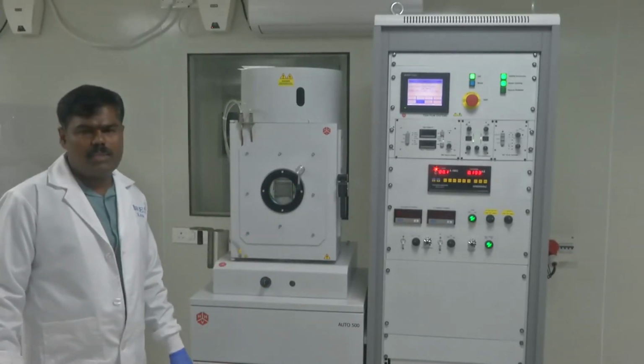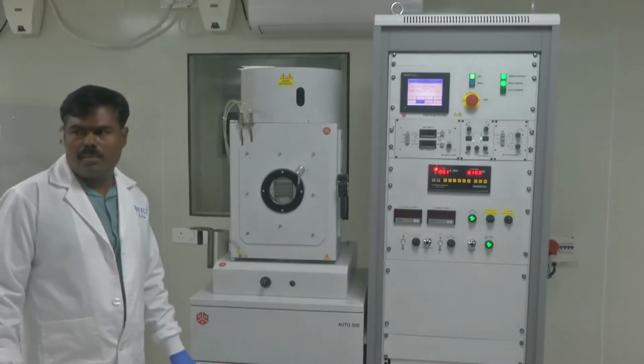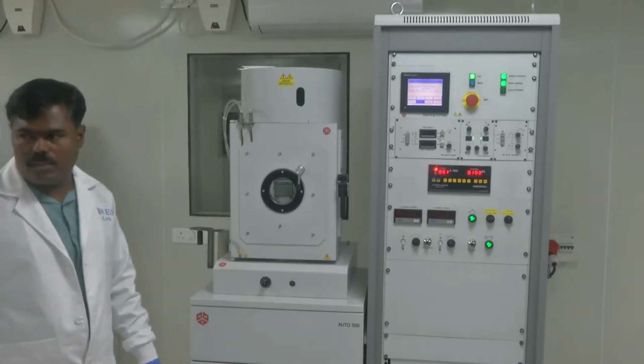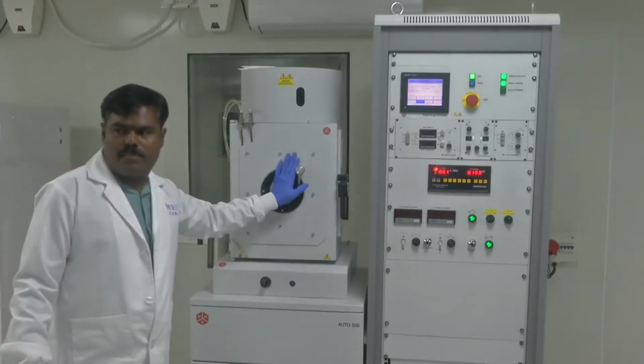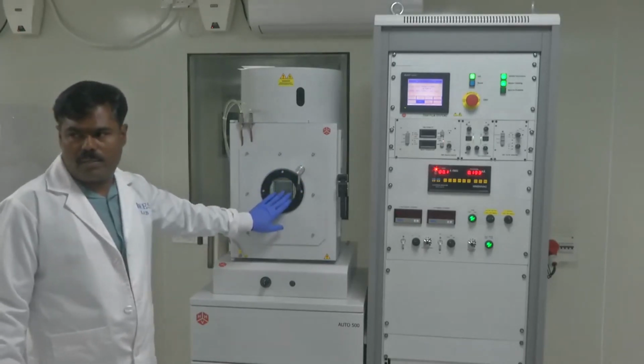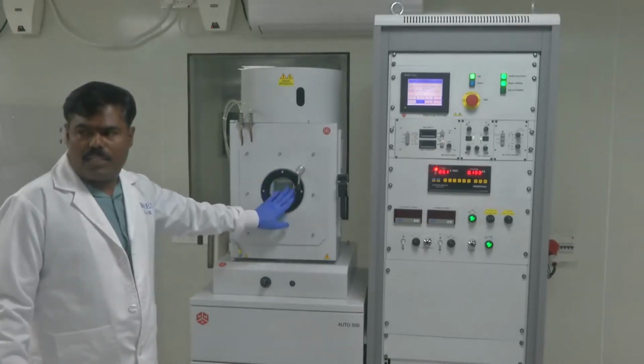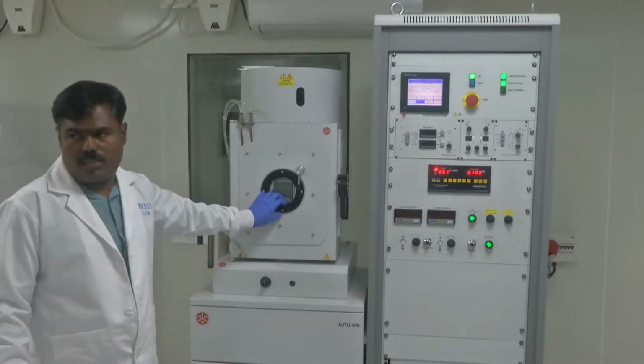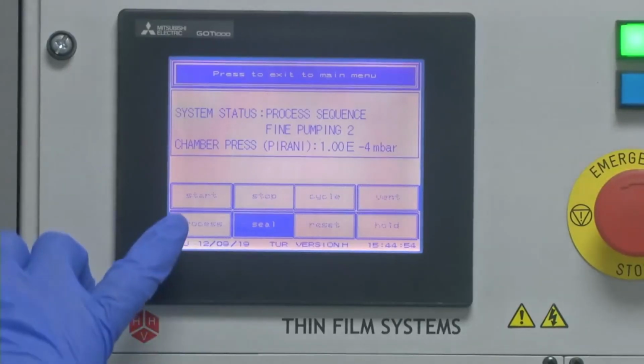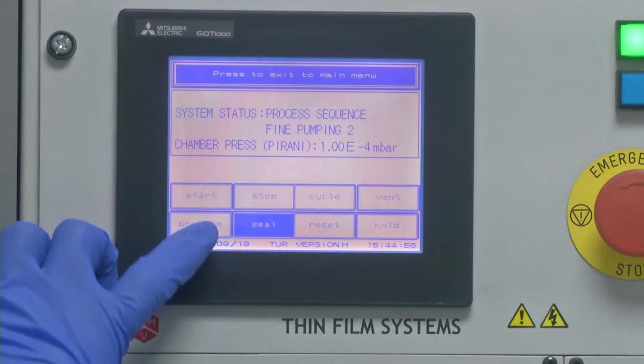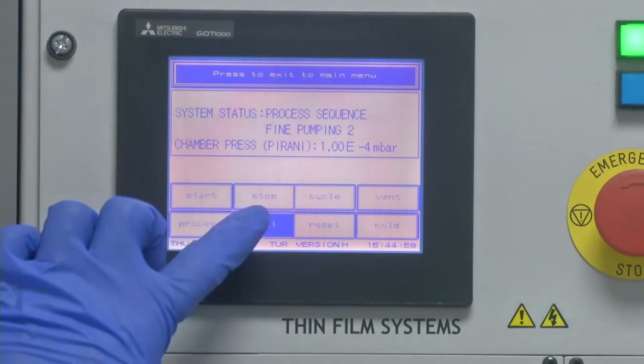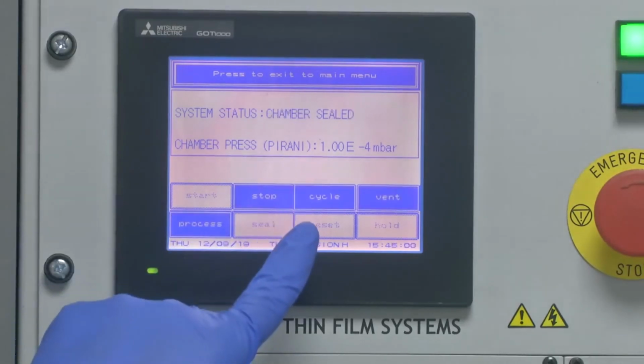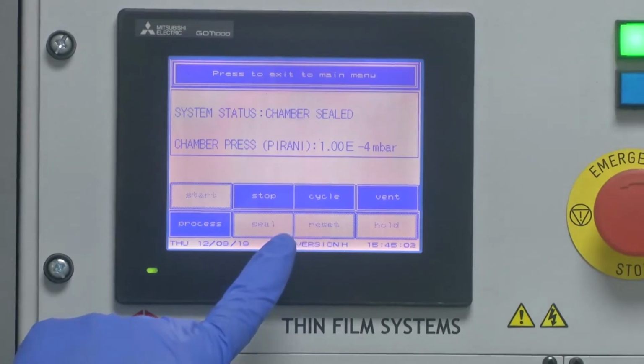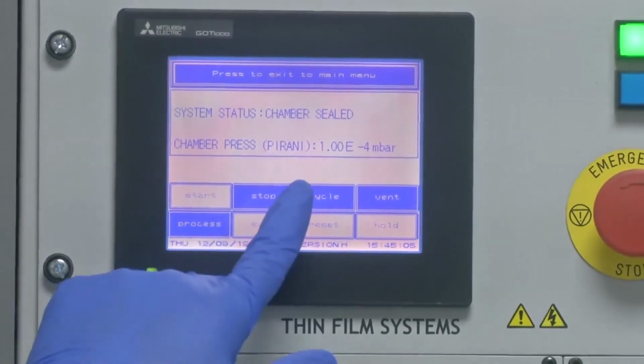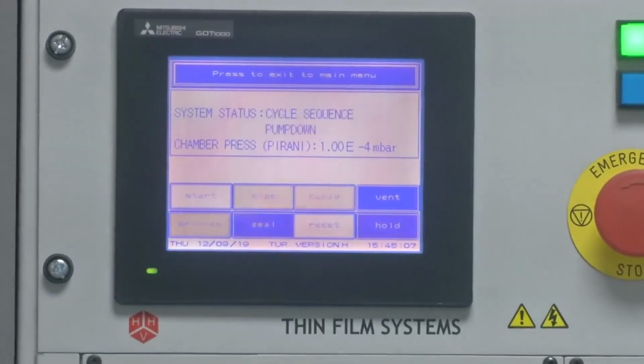So to avoid that, better to keep it 10 to 20 minutes under high vacuum cooling. Keep it as it is. Do not open the chamber after finishing your deposition process. Once your process is over, press the process, then go into cycle.